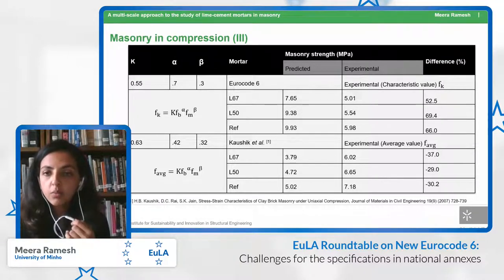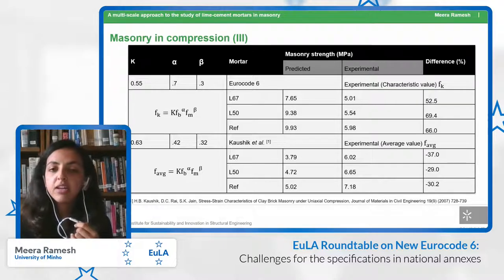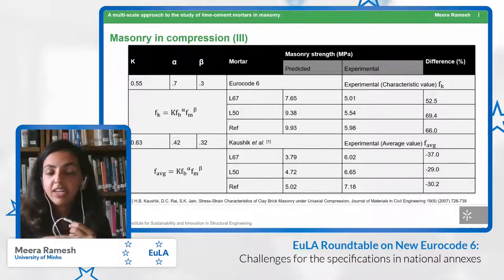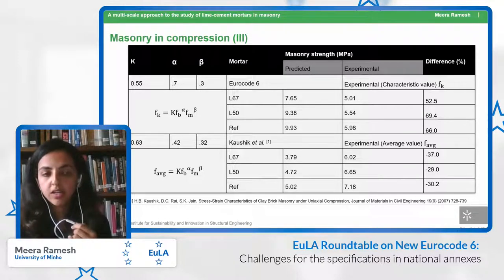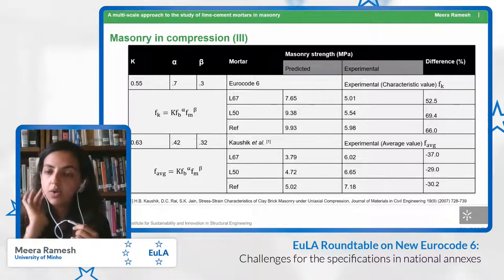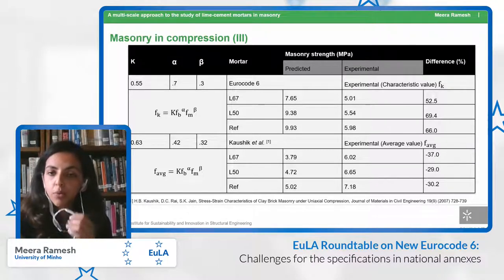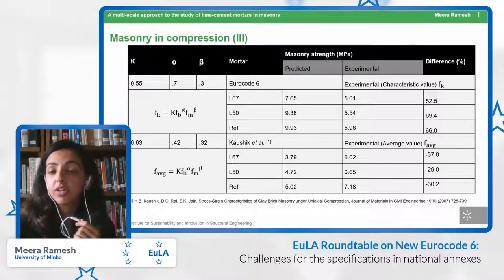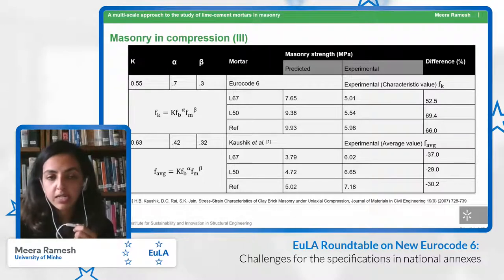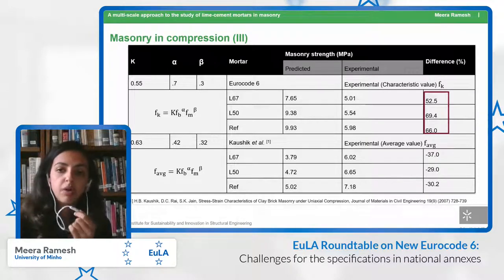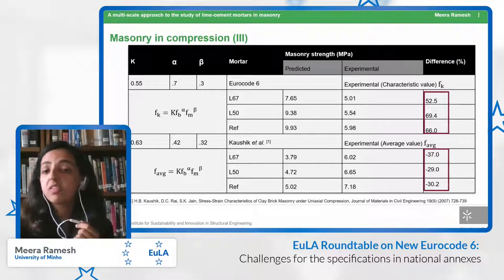We also compared them with the work of an author, Koshik, whose work has also been used by several other authors. And we found that in his estimations, the values were underestimated significantly. So we could not find a good analytical expression to estimate the strength of masonry. But the important thing here is that Eurocode overestimated what we obtained experimentally by a margin of 50 to almost 70%.